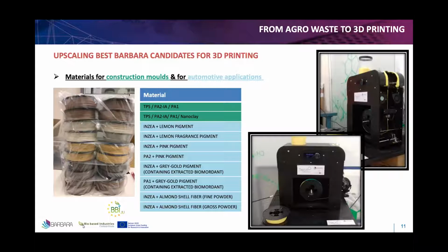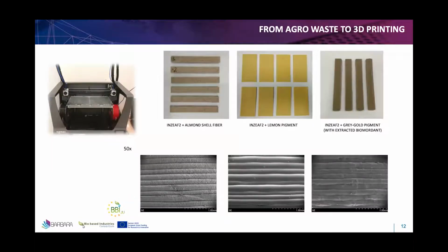And here you can see a list of the materials that we obtained based on the INZEA, which are the polysaccharide-based materials, and the different polyamide-based enhanced formulations in the project. Once we had the different filaments, we had to test it in the 3D printing process, and here you can see the machine used in BARBARA. Basically, we had to validate the different materials, upscale it, and obtain different specimens for further testing and validation, apart from the final prototypes.